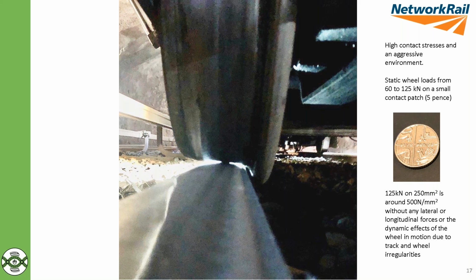The contact stresses at those points, perhaps around 500 newtons per millimetre squared, something approaching the yield strength of the material, even as a static load. When you start to increase that because of roughness, dynamic loading, the forces increase quite dramatically. So quite a challenge there, and just a striking picture I was sent showing that the very small contact area, about the size of a 5p piece, a coned wheel on a crowned rail in that situation. But yes, asking a lot of the materials in that situation, particularly when we repeatedly run over the same location.